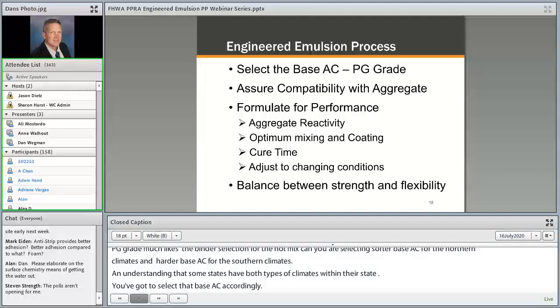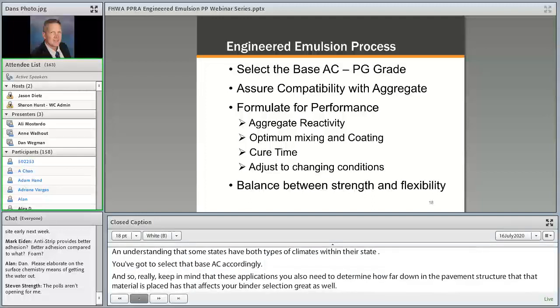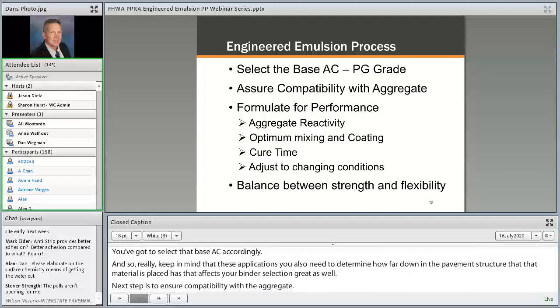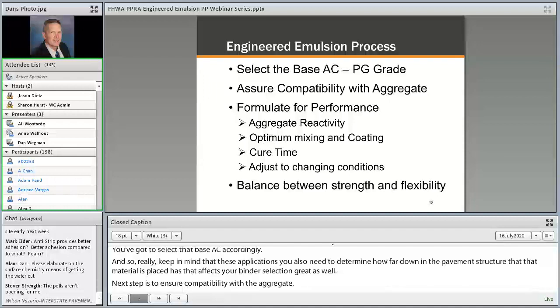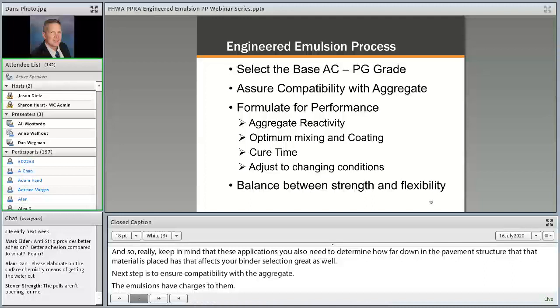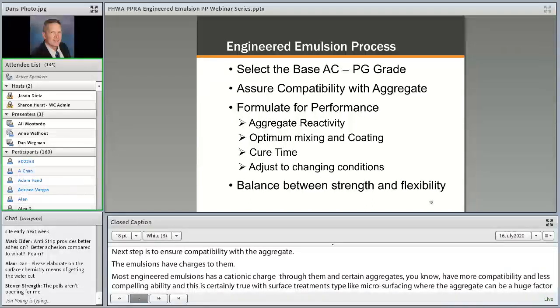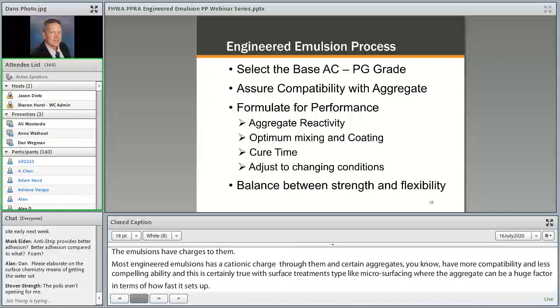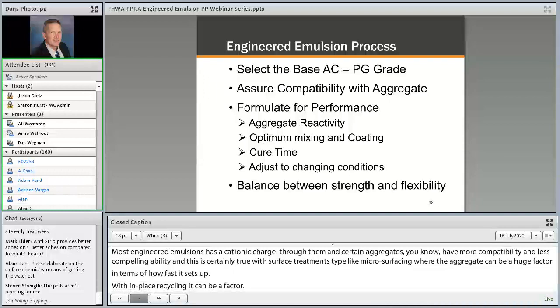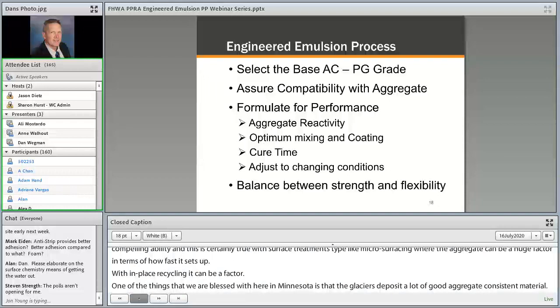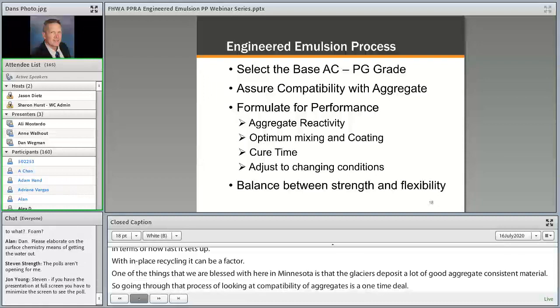Next step would be to assure compatibility with the aggregate. As we mentioned, emulsions have charges to them. Most engineered emulsions that I'm aware of have a positive cationic charge, and certain aggregates have more or less compatibility. That's certainly true with surface treatment type applications like microsurfacing, where the aggregate can be a huge factor in how fast it sets up. With in-place recycling, it can also be a factor. One of the things that we're blessed with here in Minnesota is that the glaciers deposit a lot of really good aggregates, consistent material, so going through that process of looking at compatibility of aggregates was pretty much a one-time deal, and now we can use that information to formulate going forward.